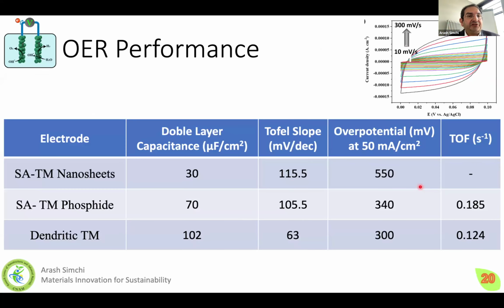I would like to show you the oxygen evolution reaction performance. Very simple. Here are the nanosheets. Here is a phosphide, and this is the dendritic state. And you see here the double layer capacitance, which we measure by cyclic voltammetry, as you may be familiar with. We just do cyclic voltammetry at different scan rates. And double layer capacitance is related to electrochemical active surface area. So we show that by making a dendritic structure, we can almost multiply the active surface area by 3 or 4. And you see the Tafel slope, which shows the barrier against the kinetics, drops by half, while the overpotential decreases significantly, and the Tafel slope again decreases significantly. So what does it mean?